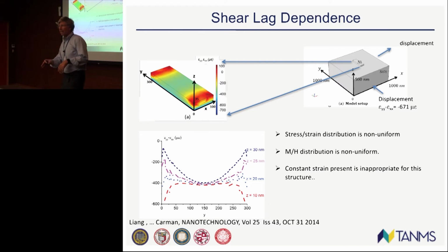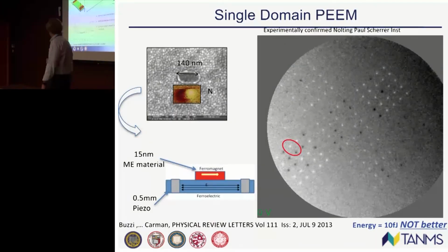But what's really funny is the magnetic community has the same thing. What do you all call it? Demag effect, right? What's the condition here at the free edge? The normal component of flux has to be continuous, and that actually sets up demag terms. So you actually have this thing that the magnetization rolls off, and in the middle you actually have uniform. Those two features are what add in this small scale phenomenon. Now once you have that, now you can go back and actually make a structure and see if you can turn off magnetism in the small scale.